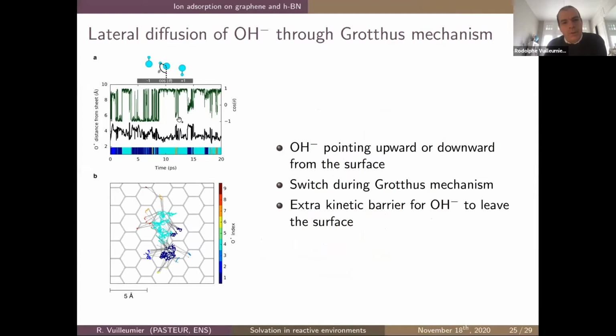And we could look at these hops, where there is a Grotthuss mechanism again, but on the surface now, because the OH minus is still trapped on the surface. What goes on is that during the hops, there is a switch of angles between 0 and 180 degrees with respect to the surface, such that when the system goes higher, it cannot diffuse away because it doesn't have the right orientation to do further hops toward the bulk. The only hops that it can do is to go backwards closer to the surface. So it oscillates between two positions close to the surface. And so we have transport of OH minus also on the surface.